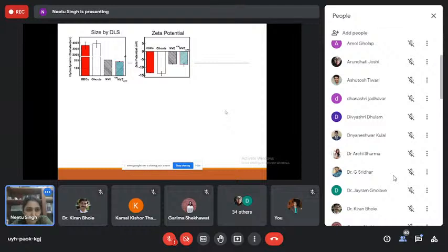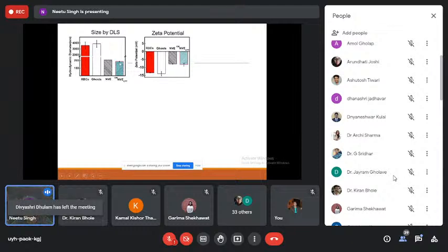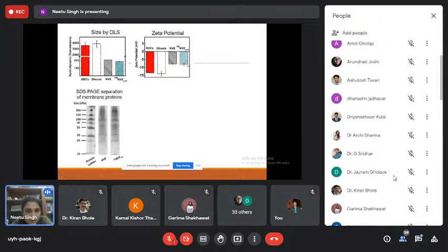Okay, you can see the size. So this is your RBCs in microns. You have your ghost also in microns, but the nanoparticles were about 200 nanometers in diameter. And once you put the drug and the dye, we thought that it might rupture the assembly process. It doesn't. It actually is in a similar range. The zeta potential is basically all negative because remember it's a cell membrane, so it'll be negative in charge.